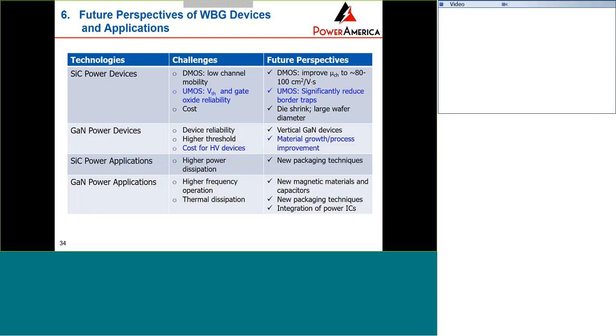So the reason behind that, for high voltage gallium nitride devices, it may have some reliability concern in the material growth techniques or the buffer layer quality. So in addition to the surface passivation and the surface issues induced field crowding, I would think the reliability could be at least one major concern for the wide adoption of the gallium nitride power devices, especially for high voltage. Okay, thank you. That's the end of the written questions, but a lot of people have dropped off, so